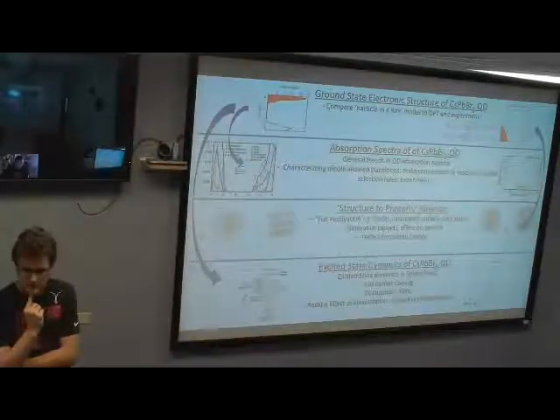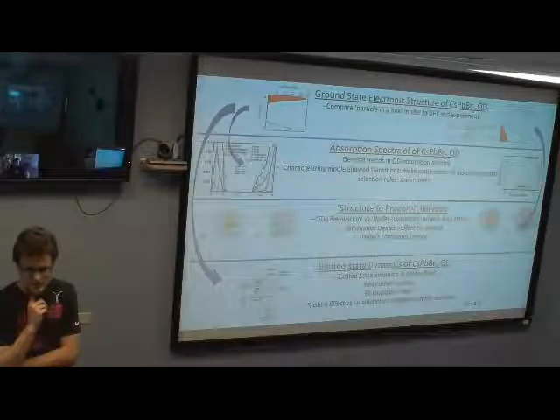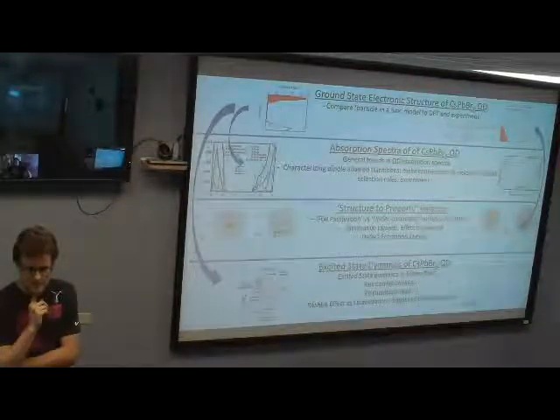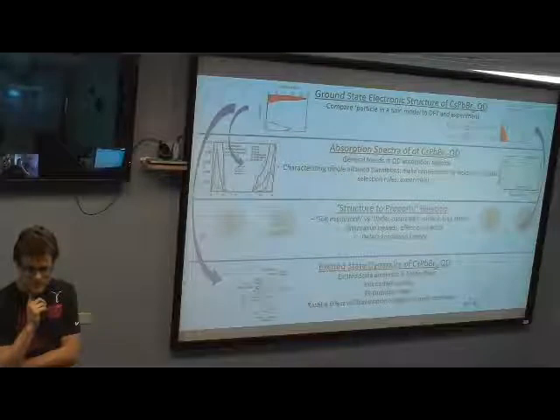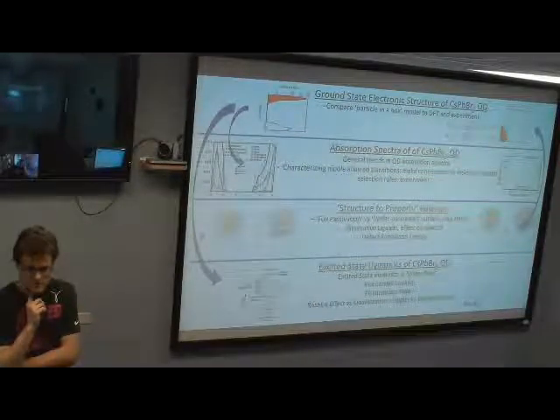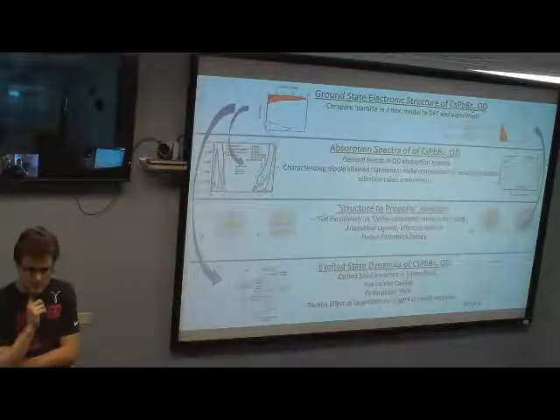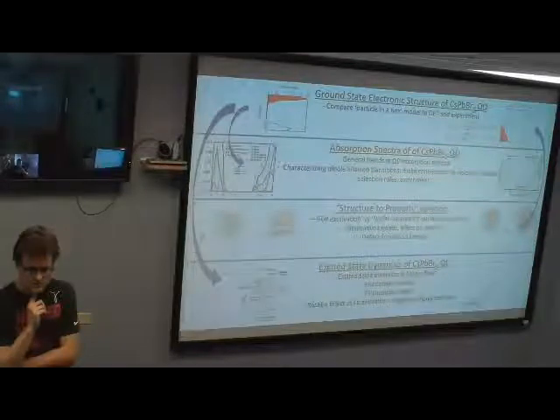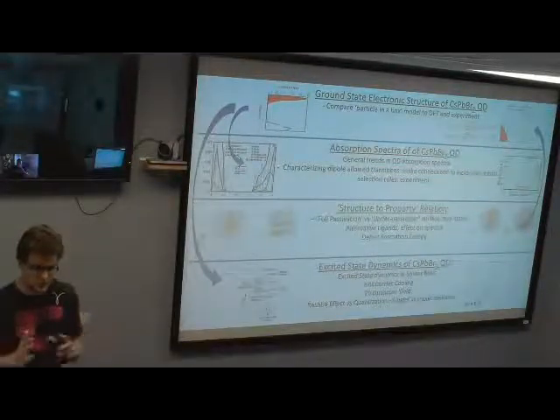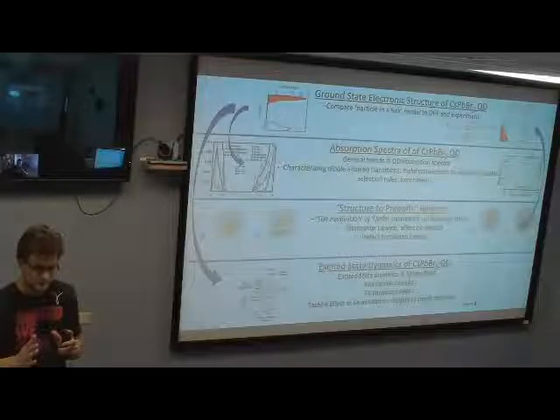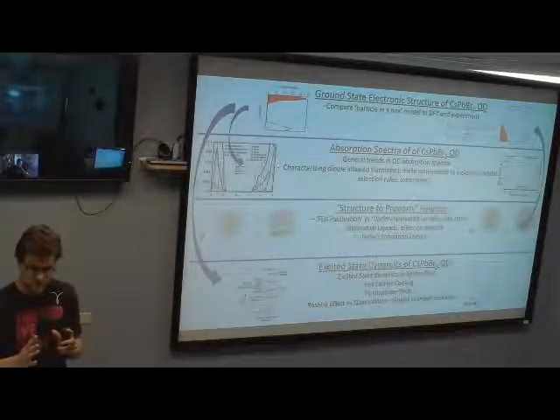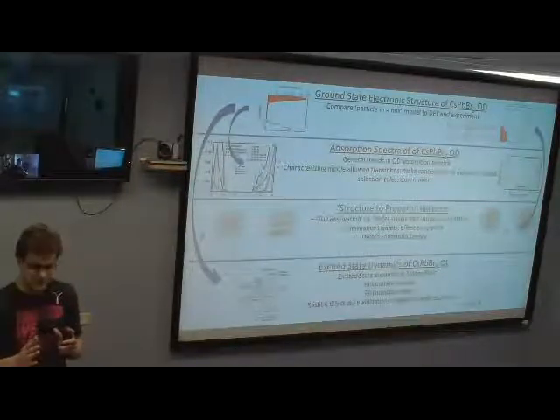If you just look at the model of quantum confinement, let's say you make your perovskite start with a bulk, where the relaxation is very, very slow. And then you go smaller, smaller, smaller to really nanometer sizes, right? So just using the knowledge of quantum mechanics, what would be the effect of this confinement on relaxation rates, intuitively? You squeeze your charges together so they're more likely to scatter off each other or interact, so I guess non-radiative relaxation would increase.